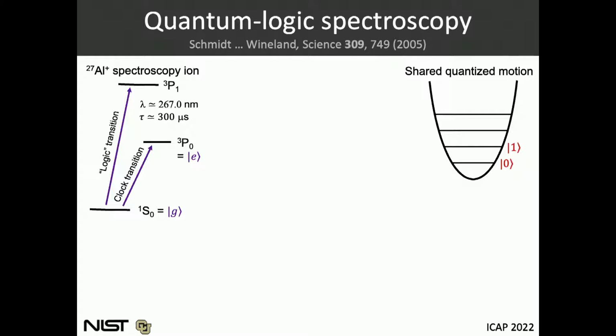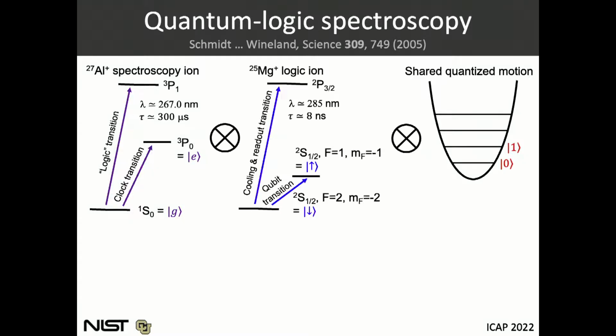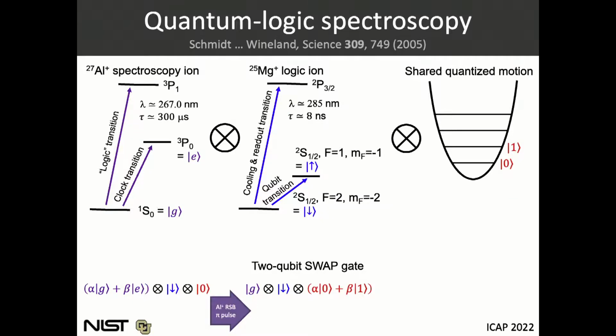So in this technique, we have the aluminum ion. We have this quantized motional mode. It's a harmonic oscillator. And then we have our logic ion here, and I'm showing magnesium. So the way this works is that we first start in some unknown superposition state of the two clock levels of aluminum. We attempt to drive a motional sideband transition on this logic transition of aluminum, which adds a phonon of motion if and only if the aluminum ion started in the ground state. And then we can map that phonon of motion onto the magnesium qubit transition here and read this out with standard fluorescence techniques.